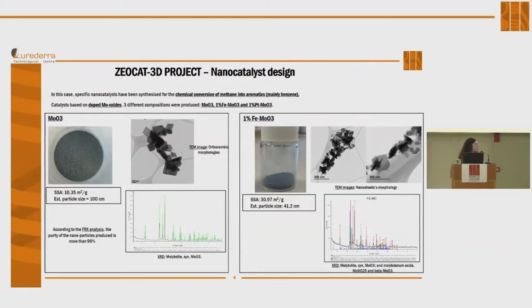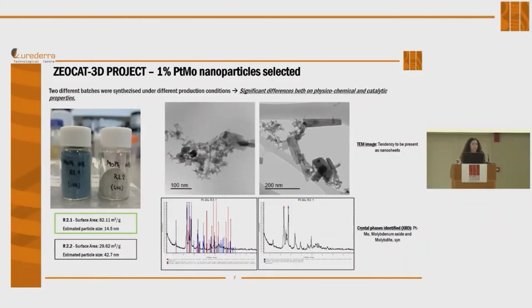With the introduction of iron, in a percentage of 1%, we get a reduction of the particle size and a higher surface area of this material. There were other options of dopants, for instance platinum molybdenum, that in some catalytic tests carried out by the University of Poitiers, we saw this dopant was better in its catalytic behavior for this reaction. So we finally selected this platinum doped molybdenum nanoxide.